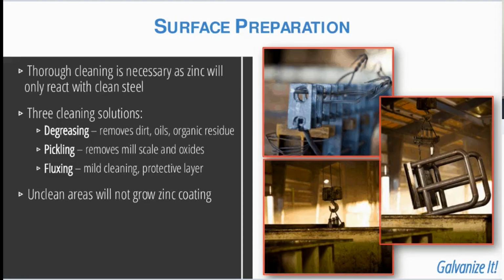First, the surface preparation stage, that's really the most important stage because zinc is not going to react with unclean steel. So the pretreatment process itself involves three steps to ensure that you have a clean steel surface. The first is degreasing, which removes dirt, oils, and organic residues. Then the acid pickling step, which removes mill scale and oxides. And then finally fluxing, and this removes any remaining oxides, but also provides a protective layer on the steel in order to prevent any further oxides from forming until you can immerse that material in the galvanizing kettle.